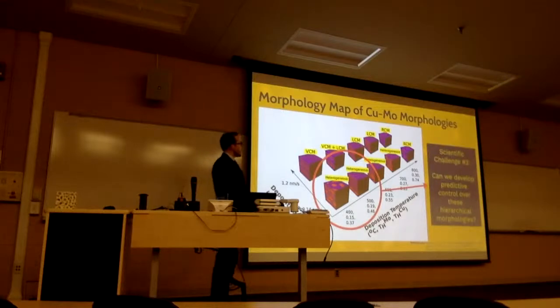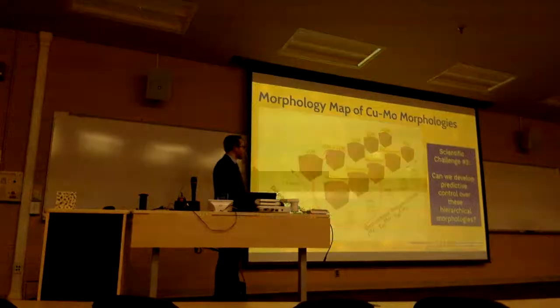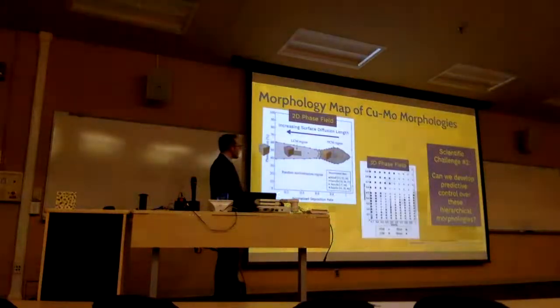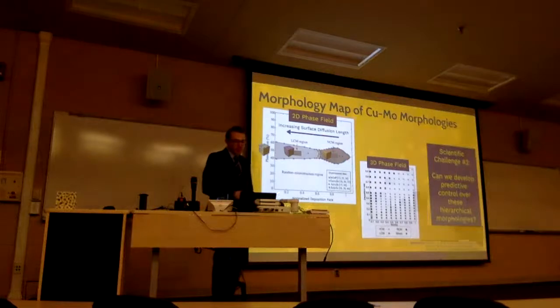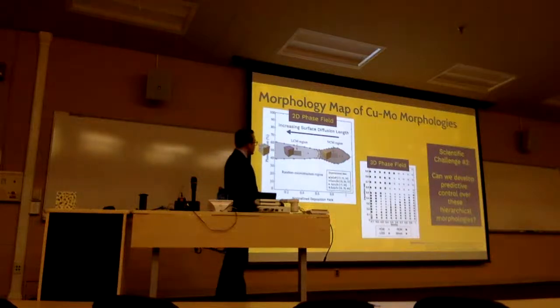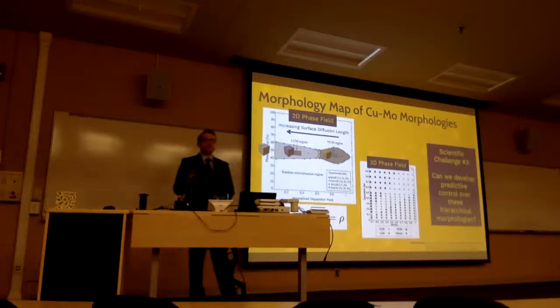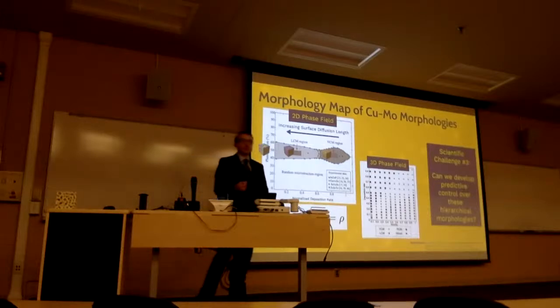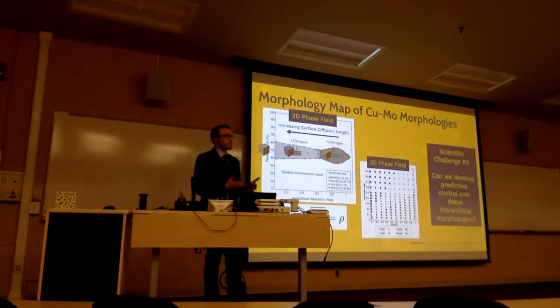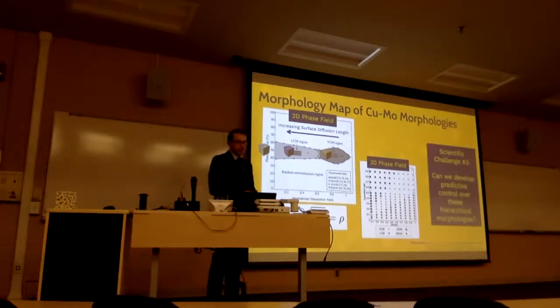But the scientific challenge is, can we develop some sort of predictive control? None of the models that we described before predict this sort of morphology. Neither the 2D phase field or the 3D phase field simulation that we did. Now, what's really interesting is that both of these models actually describe a single surface interdiffusion length, which is actually an average between the surface diffusion lengths of both of those constituents.